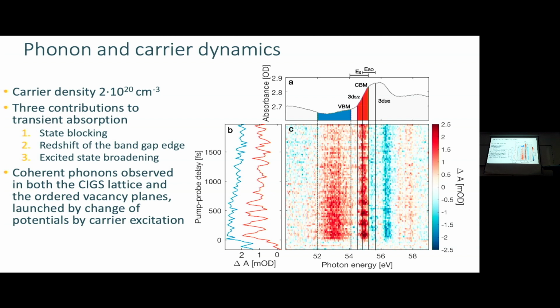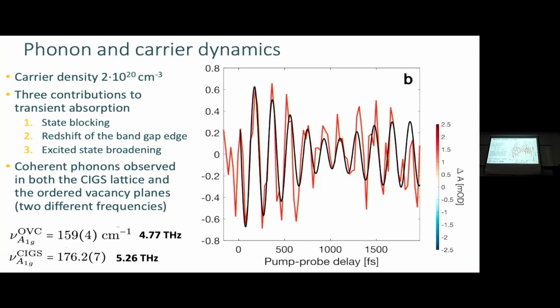So if we look at the phonon and the carrier dynamics, which we've done, we see immediately that there's coherent phonons happening. So time again goes up. And whenever you see this blinking, you know that there's something new happening with the coherent phonon on the right time scale. And we can get the line outs of these and so on. And what you find is that when you analyze the coherent phonon, you get two different frequencies, one for the normal CIGS and one for where the copper is deficient. They call it the ordered vacancy compound. This is the copper deficiency. So you get 5.26 terahertz and 4.77 terahertz.